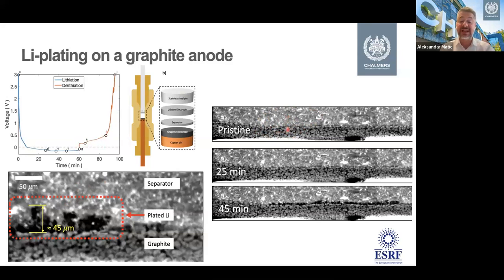But you can see that with cycling, with time, approaching somewhere around this point, we see a black layer appearing here. And this is the lithium metal now being deposited on top of the graphite. So you can see here, we can identify some graphite particles, but also huge metallic lithium being plated on top of graphite, and this could be done in real time.